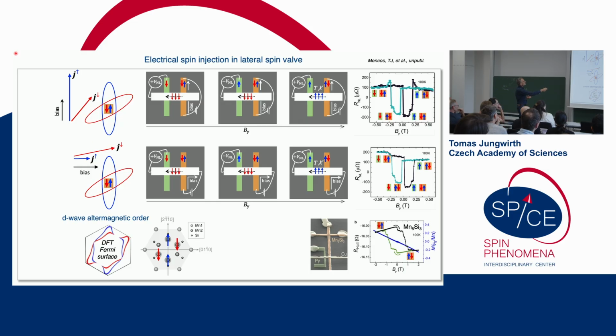Now, in this biasing geometry, again, you have different magnitudes, but also different deflection angles. So you have not only the longitudinal part of the electrical currents in the 2 channels, but you also have a transverse component, in particular for the spin down electrons. Just finishing the sentence, that explains that even if you're biasing along the electrode, you will have a component of a spin polarized current which is going into the channel.